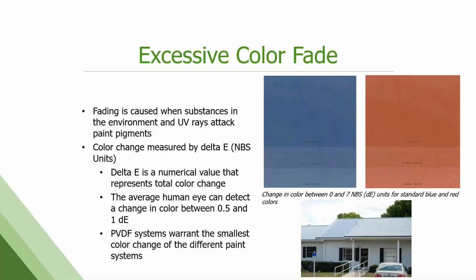The other thing we notice with color fade is that if the color fade over time is pretty even and consistent, usually no one complains. We usually get color fade complaints when, like with that house in the picture, part of the roof is doing fine and part of the roof is not, and it becomes obvious that something's going on. But if you're 30 years in on a roof and it's faded pretty evenly, probably not going to get a warranty complaint.